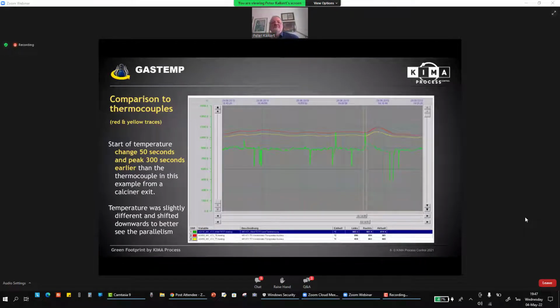Here you see another example. In this case, this was a measurement of the secondary air at the outlet of a kiln. The top two traces show two thermocouples which were above the measurement of our acoustic device. You see red and yellow show a pretty nice temperature of around 1100 degrees centigrade. I would like to point your view to this time here. You see something was happening at that point, and the temperature of the acoustic system rose pretty fast, and the thermocouples realized this only several minutes later. It was more than 5 minutes.